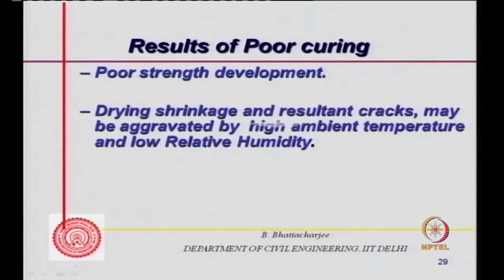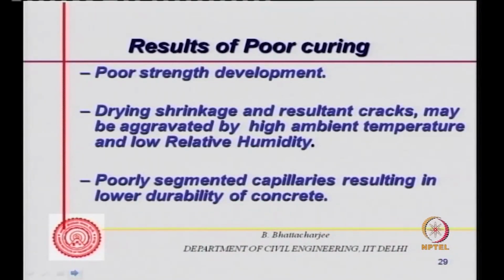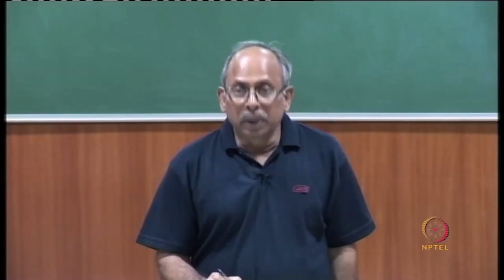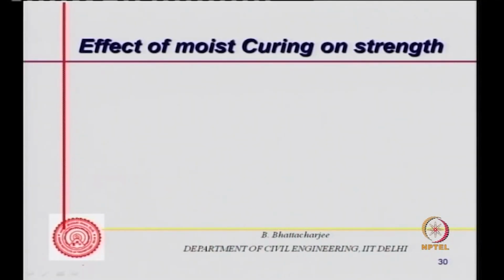So if you have not done good curing, what will happen? Obviously, strength development would not be there because hydration has not occurred. A lot of pore space will remain, and drying shrinkage can result because the water has gone out, and this can result in cracks. It may be aggravated by high ambient temperature and low relative humidity. Poorly segmented capillary results in lower durability of concrete. So this is the effect of curing.